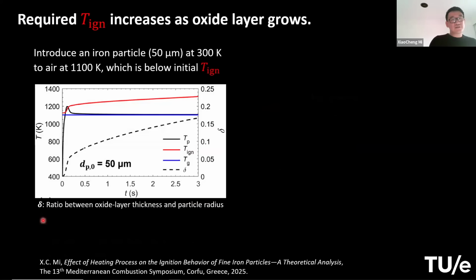And to this, I recently did a theoretical analysis. I just did a thought experiment. Let's say you have a particle, 50 micron, initially at room temperature, and then you introduce that to air that is at 1100 K, which is actually below the critical ignition temperature. So the particle won't be able to ignite.